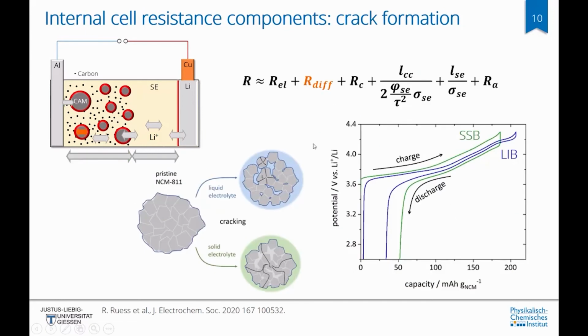Now we have a look at the diffusion resistance inside the cathode active material. And here we found that, comparing liquid electrolyte and solid electrolyte cells, the performance to be worse with NCM multicrystalline materials for the solid-state battery. We were able to attribute this to the internal cracking of the NCM particles during cycling.